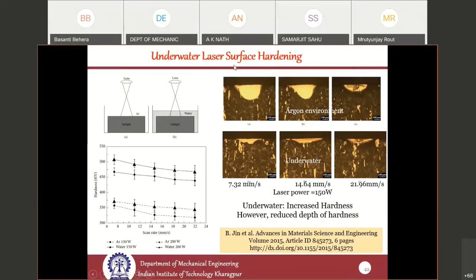This shows underwater laser surface hardening. When you use underwater laser surface hardening, you depend on fast cooling in the bulk material. Inside the water, the cooling effect becomes much more rapid, and therefore the micro hardness generated is much higher compared to what you can generate in air. These two graphs show micro hardness in air versus inside water. Though the depth reduces because of a certain amount of absorption of laser power in the water, the magnitude of the micro hardness increases.